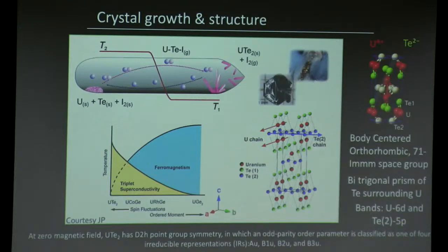The bands that live close to the Fermi energy are the uranium 6D bands and the tellurium 5P bands, and these are hybridized with each other. The Fermi surface is not very complicated, but these are the bands close to the Fermi energy. Additionally, it's a heavy fermion compound, so there's the F state that at low temperatures also lies close to the Fermi energy.